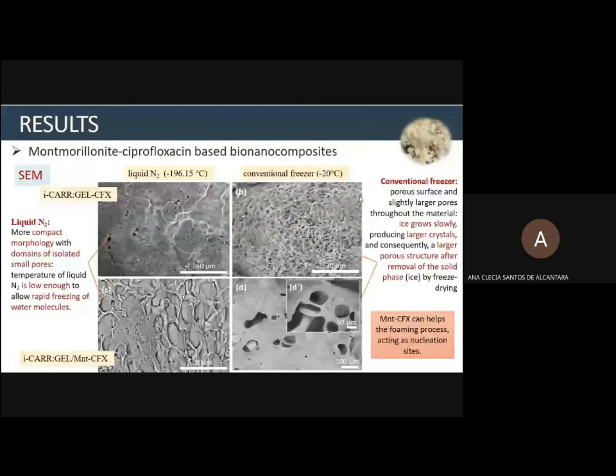Differences in the porosity of the beads can be attributed to the growth rate of the ice crystals. In the case of liquid nitrogen, the temperature is low enough to allow the rapid freezing of the water molecules, not allowing indiscriminate ice growth. Conversely, in conventional freezing, the ice grows slowly, produces larger crystals, and consequently a large porous structure after removal of the solid phase by freeze drying.